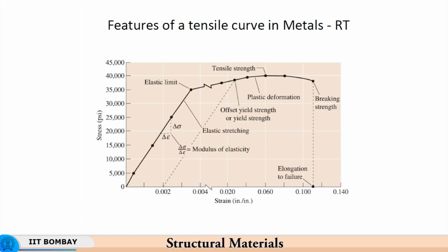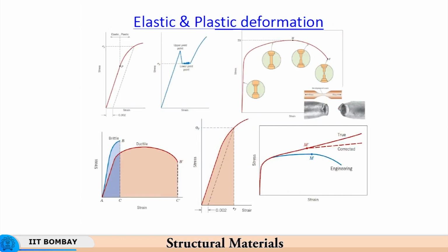Now, if you look at the elastic and plastic deformation in greater detail, this is a typical curve for mild steel. This type of yielding is seen in mild steel, where you have a sharp upper yield point and a lower yield point. Usually the lower yield point is quoted as the yield point for steels, and then after this the plastic deformation starts. So, you have an upper yield point and a lower yield point, and this is what is called the yield point phenomenon, which is also called static strain aging, and this is responsible for a defect called Luder's bands.